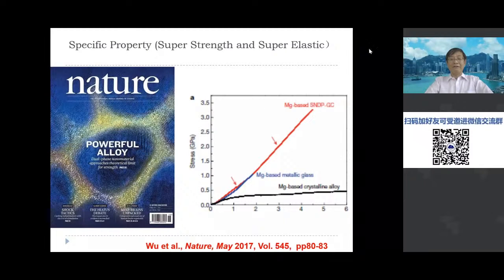Okay? So the first material we have developed is a magnesium copper yttrium alloy. As you may see here, the blue curve is the magnesium based metallic glass. And our new alloy has mechanical properties much higher in terms of elastic yield stress and deformation capacity. From a structural viewpoint, we can see this material is quite homogeneous, and the blue part is a nanocrystal, the size is around 6 nanometers. And the yellow part is metallic glass with another composition. And this material provides this excellent mechanical property.